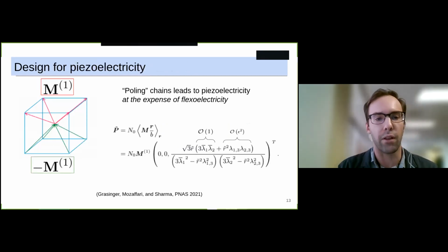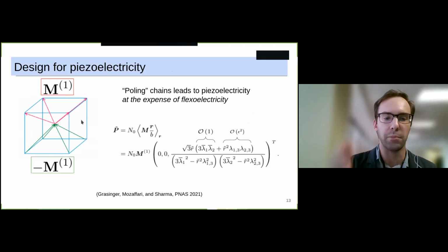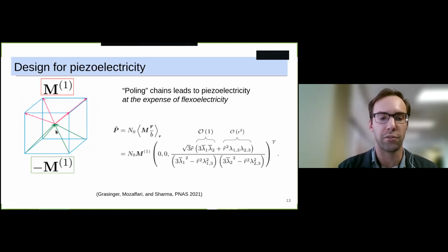We've also thought about the problem of material design. So instead of thinking about a unit cell with randomly oriented chains, what if we introduce some order into the material? In particular, if we think about poling the chains, by poling I just mean having the chains have some preferred alignment in a particular direction. So in this case, it's in the vertical direction. We have the chains in the bottom half of the unit cell with their polarization pointing in the vertical direction, and in the top half pointing in the opposite vertical direction. What we see is that we can actually design a material that now exhibits piezoelectricity.